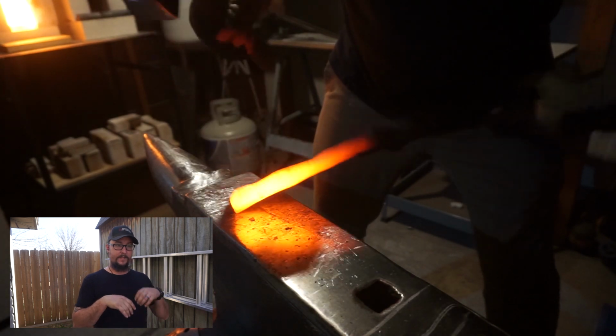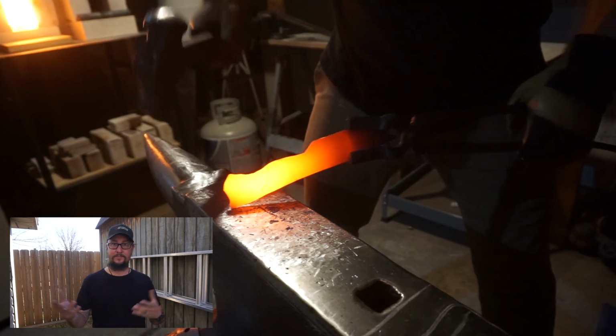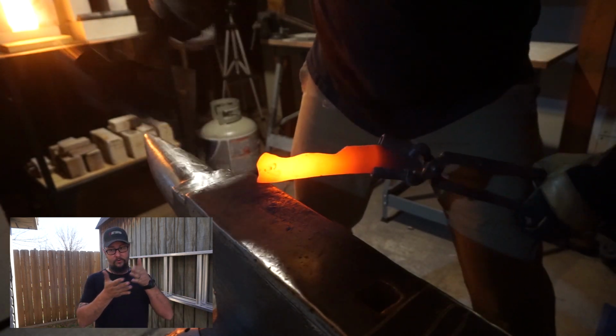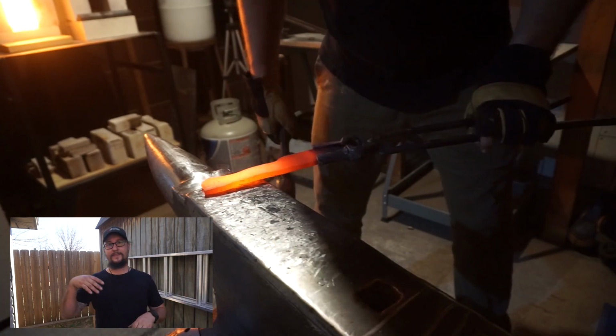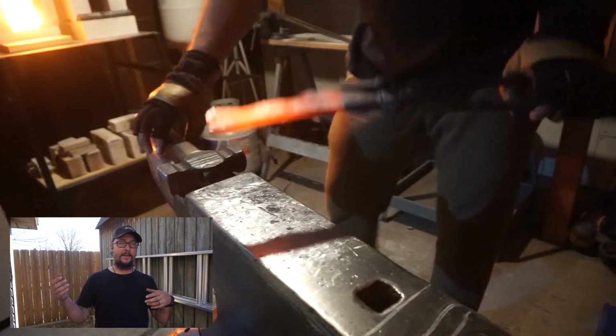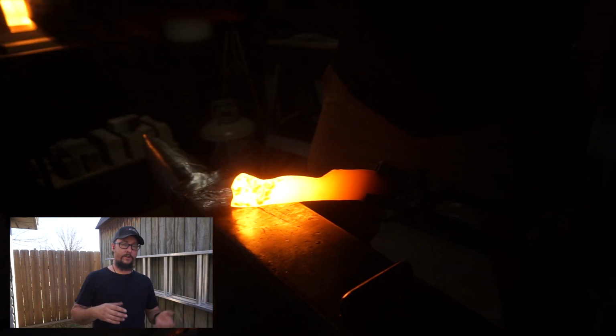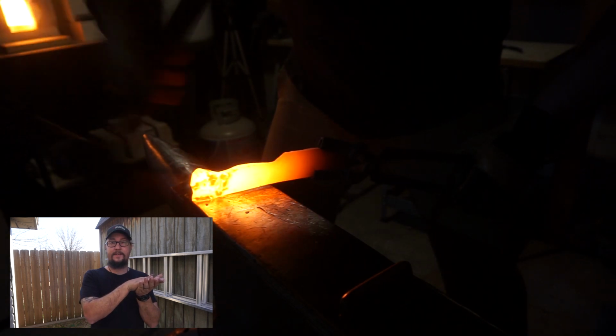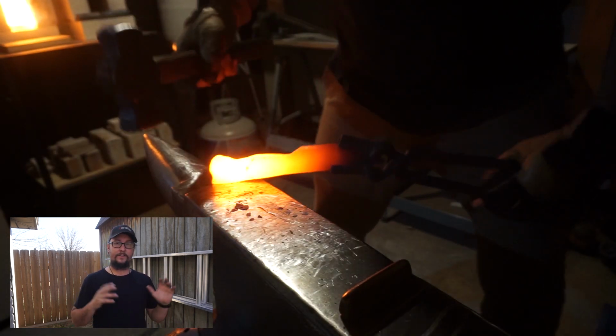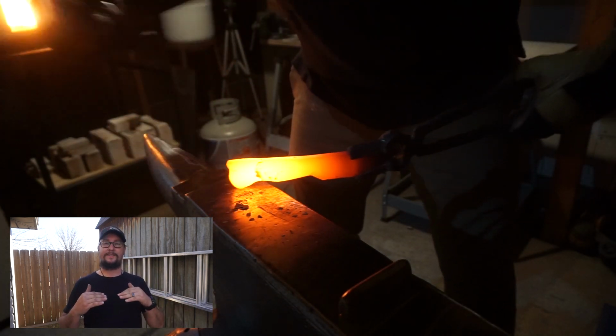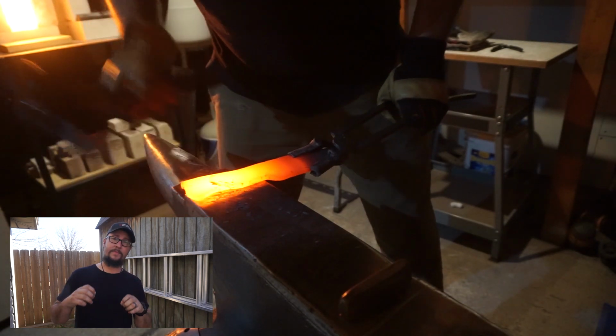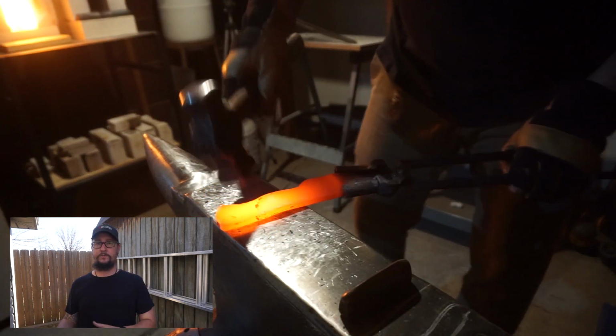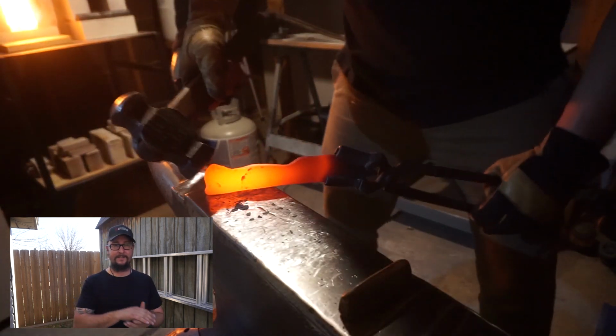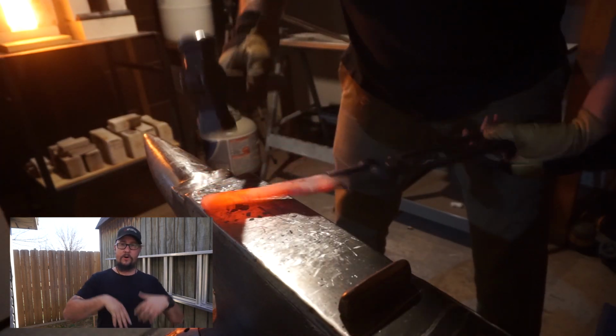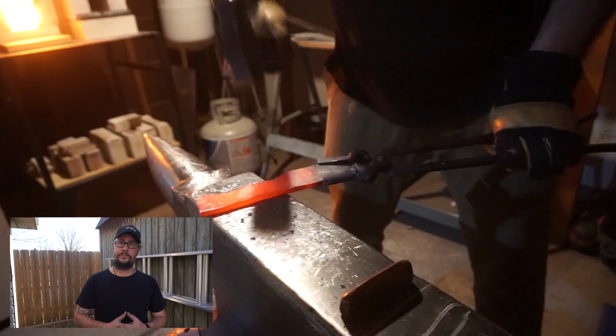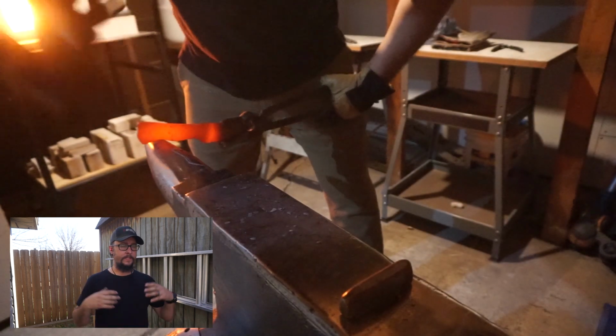But so you've got your heat treating, which is the process of bringing the steel up to temperature and quenching it in your quenchant, whether it be oil, a brine, like a salt waterish mixture, or just water, or using plates and doing it like stainless steel, and then all of the different things. Just make sure you research what process your steel needs, and make sure that you can do that with the tools that you have at your disposal. So there's heat treating and soaking. After that, once we've hardened and we've done our heat treating process, you want to make sure that you temper your steel. Now, a lot of people use toaster ovens.